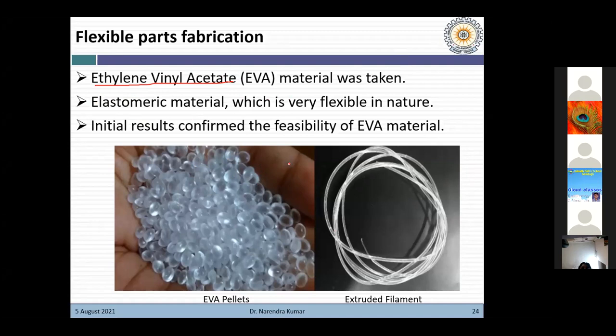So we extruded this material from our setup. As you can see from the nozzle, we got this kind of profile, in thin wire form. We initially explored whether this material is extrudable or not. It was extrudable, so we got this kind of thin wire profile in the initial experiment.